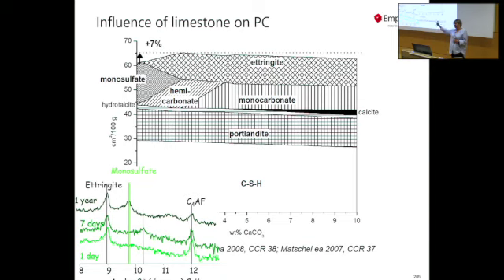So we just assumed everything has hydrated, and then we replaced 0 to 10% of the Portland cement by limestone, and calculated how that would change the composition. The main part of the cement is CSH and Portlandite, but we see a difference in the phases further above, where there is monosulfate, ettringite, and monocarbonate.